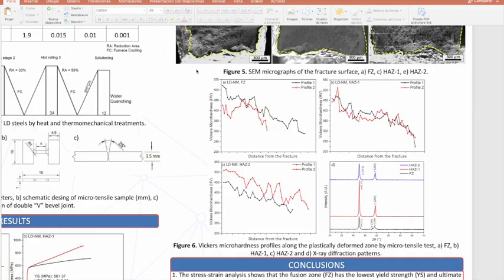Figure 6. Vickers microhardness profiles along the plastically deformed zone by micro-tensile test. Subsection A, fusion zone; subsection B, HAZ1; and subsection C, HAZ2. Figure 6 shows the Vickers microhardness profiles performed on the plastically deformed zone of the micro-tensile specimens of low-density steels. These profiles provide critical information on the variation of mechanical strength across the regions comprising the welding joint.